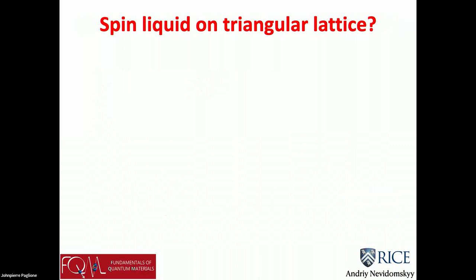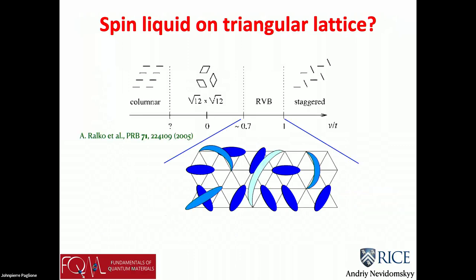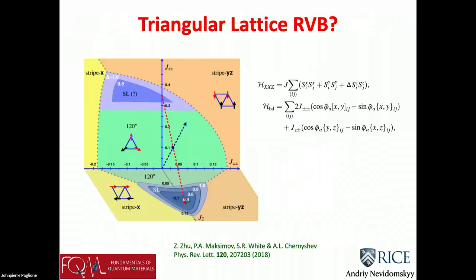Well, what about the triangular lattice? I did mention the triangular lattice to you earlier, and I showed this picture over here. Well, there has been a rich calculation. I mean, if you just start with the nearest neighbor triangular model, you would be smack in the middle of the 120 degree ordered phase, which I mentioned is just like Néel order, but with three sublattices. So you have to do something extra in order to get the regime which looks promising.